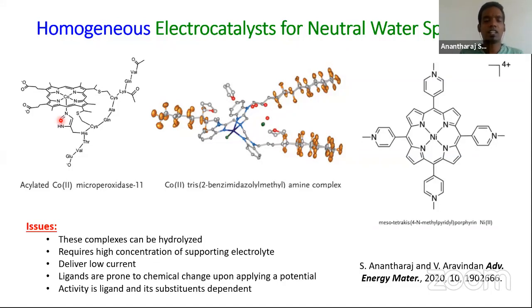Even then, it requires a very high concentration of supporting electrolyte, because the catalyst is dispersed homogeneously in water and does not have any direct contact with the electrode, and we need supporting electrolytes to give enough conductivity in order to ensure that the homogeneous catalysts dispersed in the solution experience the same potential as the one we decide to apply.